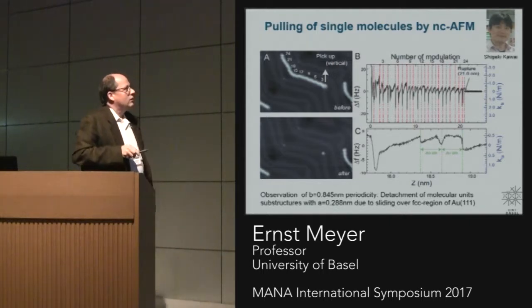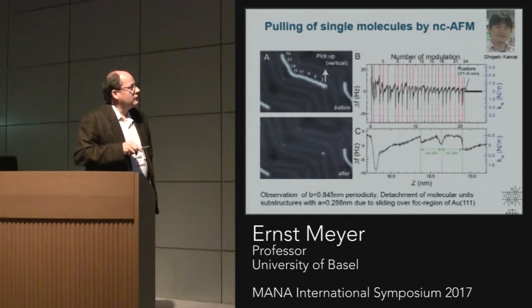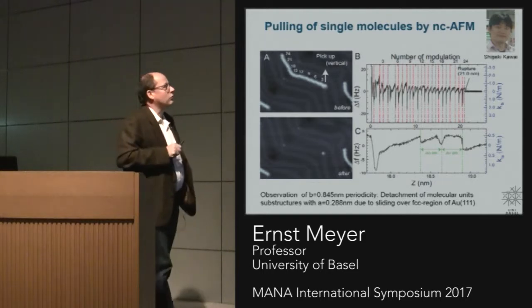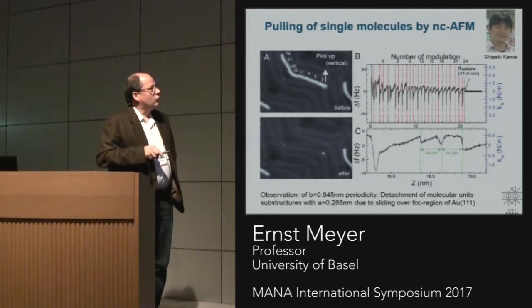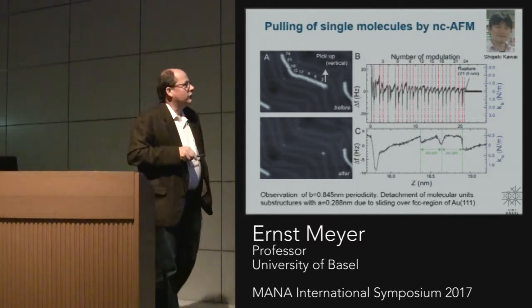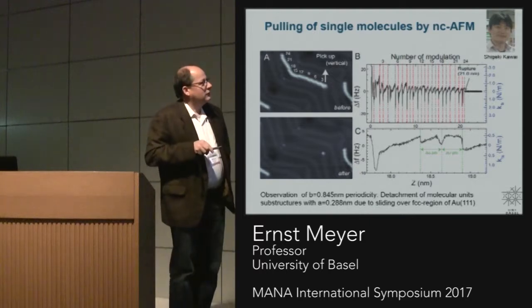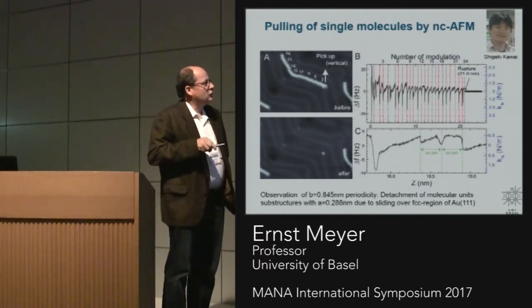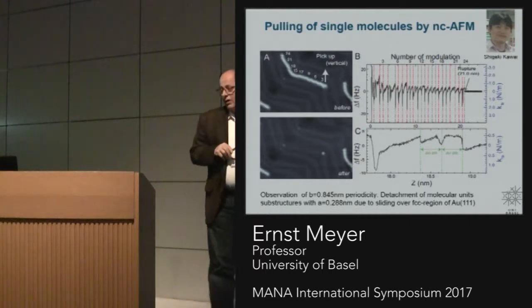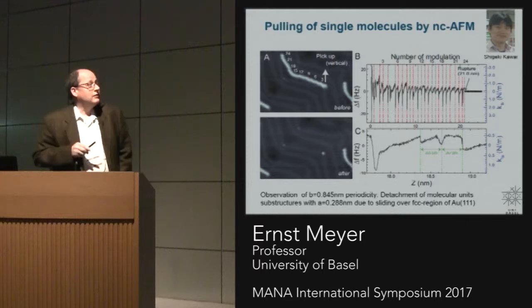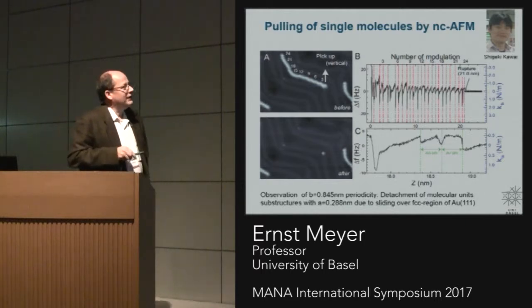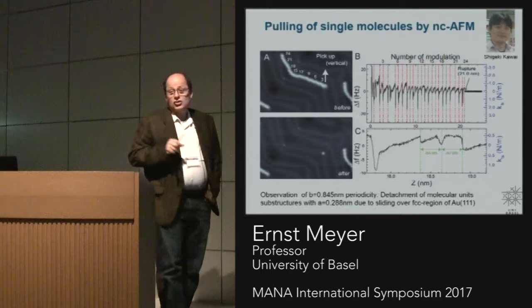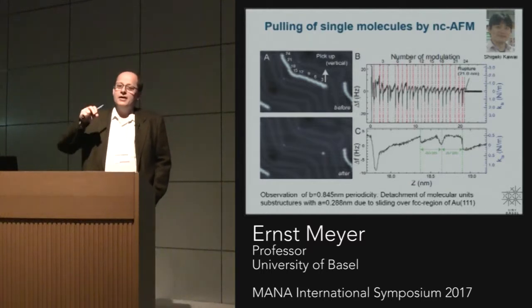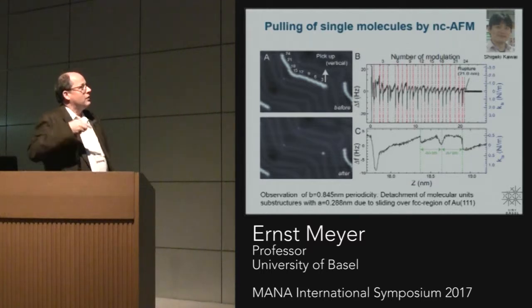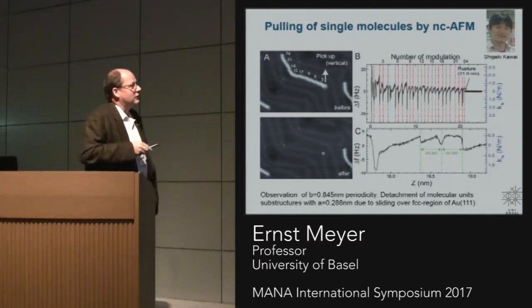And now Shigeki approached at this point here and formed a little bond to the tip, and then started to pull vertically away from the surface. And then you measure this signal, and this is what you see here. So you see really oscillation here, and if you now count this oscillation, you see actually there are 24 oscillations. And so this means the dominant effect here is actually the detachment of these units. So basically each of the subunits has to detach from the surface, and that gives you the strongest signal.